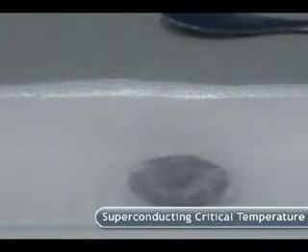When the boiling ceases, it indicates that the superconductor and the liquid nitrogen are in thermal equilibrium. This indicates that the temperature has cooled below the superconducting critical temperature of 91 degrees kelvin for the yttrium barium copper oxide compound and has established superconducting properties.